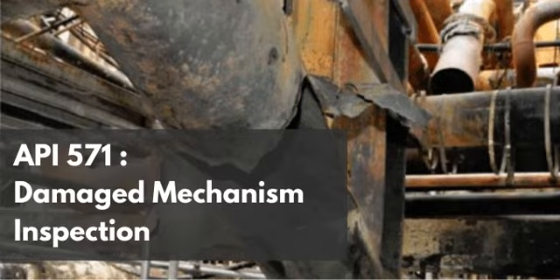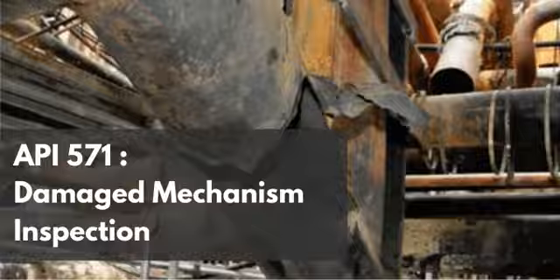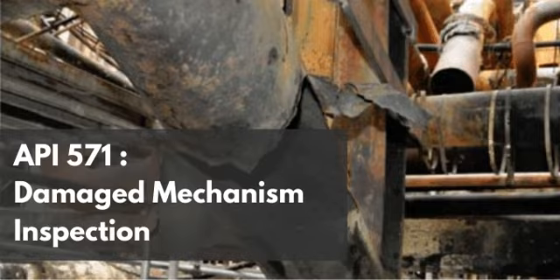Right. And when it cools back down, you've fundamentally altered the mechanical properties of the pipe. You might destroy its tensile strength or induce brittle martensite. So 1175 degrees is the thermodynamic sweet spot. It provides enough kinetic energy for creep relaxation of the residual stress, but it preserves the fundamental macroscopic strength and microstructure of the carbon steel component. Exactly. It fixes the stress without ruining the steel.